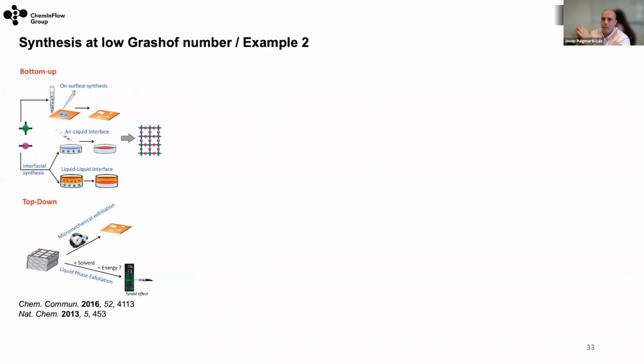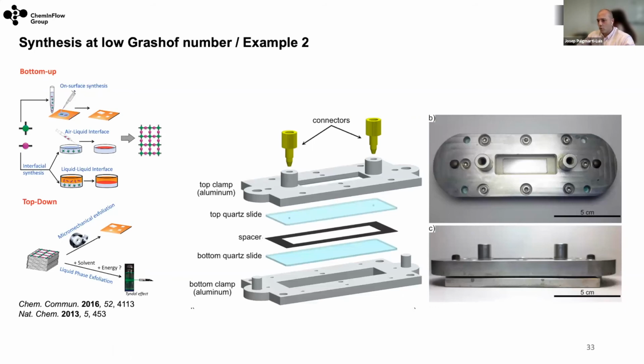So we did that with, let's say, a 3D morphology. But the idea we had in this work is, can we extrapolate that to 2D materials? Here I just gave some examples of how 2D materials can be achieved. One of the most used approaches is these two here, liquid-liquid interfaces or air-liquid interfaces. But what happens here is that you generate convection as well, because as soon as the crystal starts being generated, the reagents will be consumed, and you will have depletions and the formation of natural convection in this reaction container. So the idea was to achieve a microfluidic device that would allow us to have a low Grashof number.